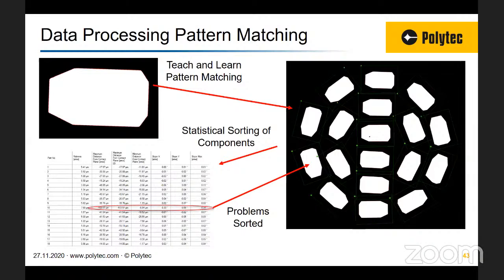So you can see here I've highlighted optic part number 10, and you can see that the maximum minimum distances from the contact plane are much higher than the other optics, and you can clearly see that this is a problem optic. This can then be remounted, and you can then optimize the manufacturing process for this particular setup. And this was something that was actively done within our instrument.